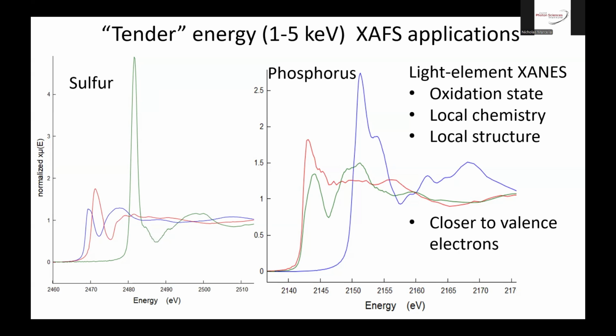Okay. It's energy dependent. For hard X-rays, it's definitely deeper. So ideally, you would want the sample thickness to be the same as the lateral dimensions of the probe beam, so that you're measuring a volume of that size. As you go down in energy to the tender energy range, that gets much shallower. So for tender X-rays, the sampling depth is a few microns generally. So you really aren't seeing much behind there.